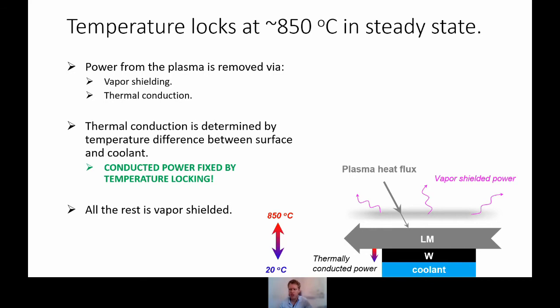So evaporation is a temperature-dependent process, and it goes as a very strong function of temperature. So even the slightest few degrees of temperature increase will give you a very large increase in evaporated particles. And because of that, you only need a very small temperature increase to have a lot more vapor shielding, right? Yeah, so you always end up around this 850 degrees C, but in theory, if you put a lot more power, it should be able to exceed this temperature, right? Because you will need a slightly higher temperature to evaporate more particles to handle higher heat loads.